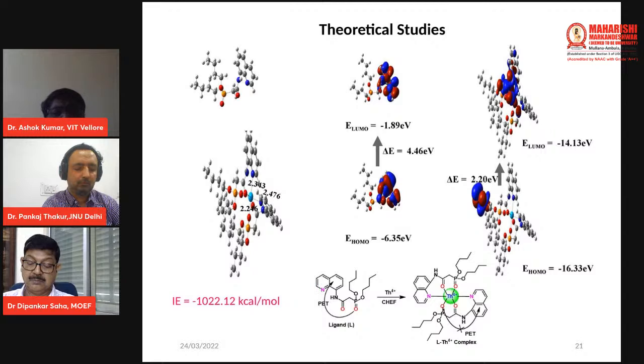After understanding those experimental details, we carried out theoretical studies. Theoretical studies show the HOMO-LUMO formations: in the case of this molecule, the HOMO and LUMO are at the same site, while in the case of the complex, the HOMO is on the quinoxyl butoxy chain, while the LUMO is forming on the thorium site.